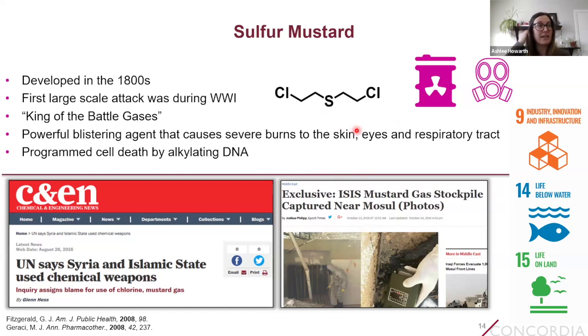And so we want to see if we can find a sustainable, environmentally friendly way to detoxify mustard gas. And the reason for that is that the traditional ways that mustard gas has been detoxified, especially bulk stockpiles, is either through dumping this compound in the ocean, where it slowly hydrolyzes and detoxifies over time, but wreaks havoc on the natural ecosystems in the ocean. And also the other way it's been detoxified in the past is through incineration. So through heating to very, very high temperatures, burning the compound, which leads to the generation of sulfur dioxides, hydrochloric acid, and toxic compounds that we don't want being released into our environment.